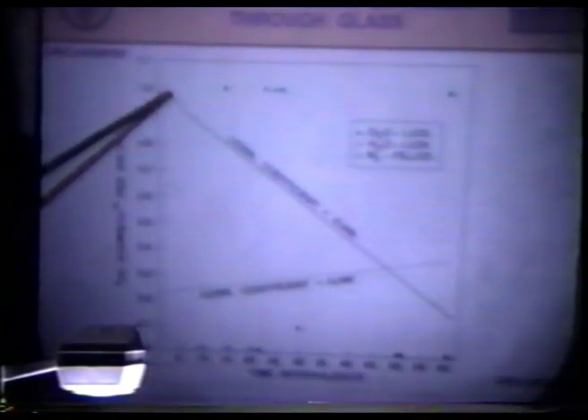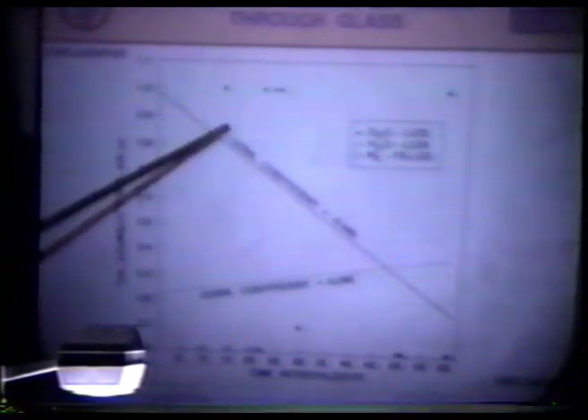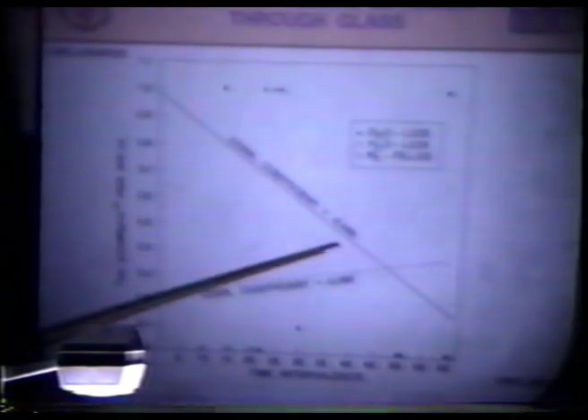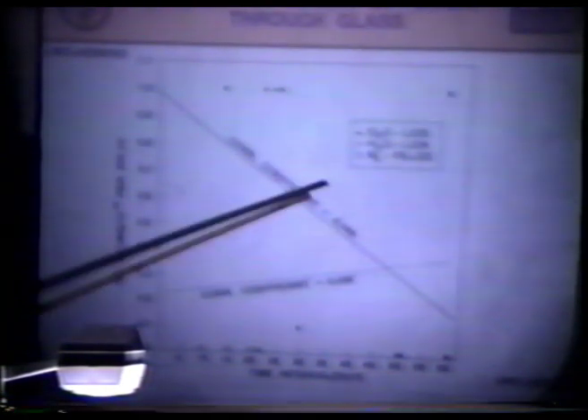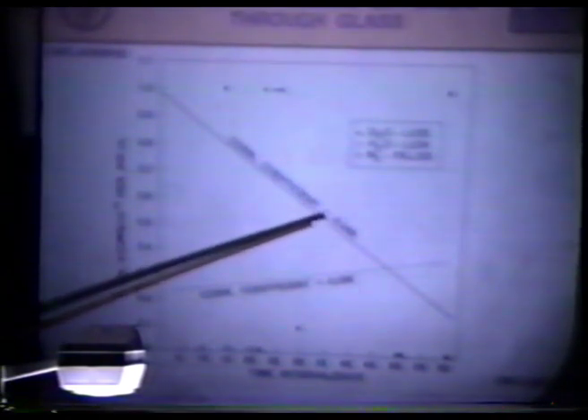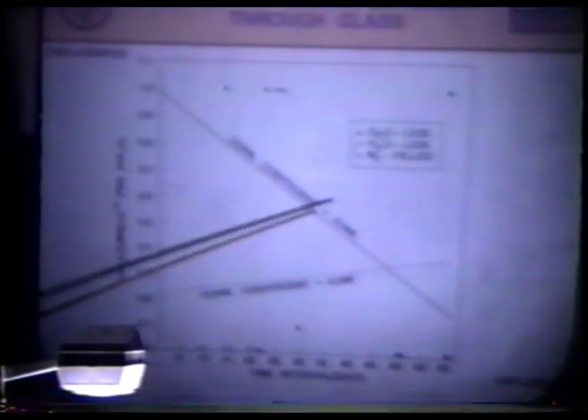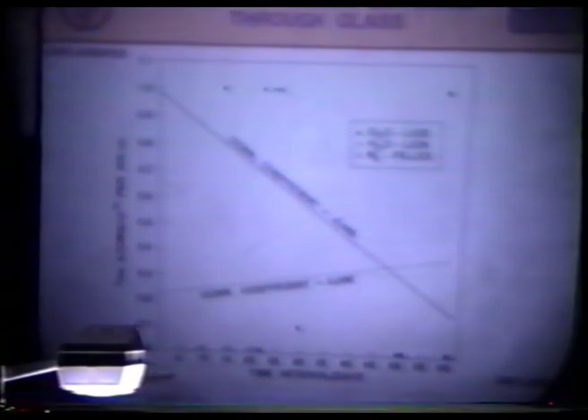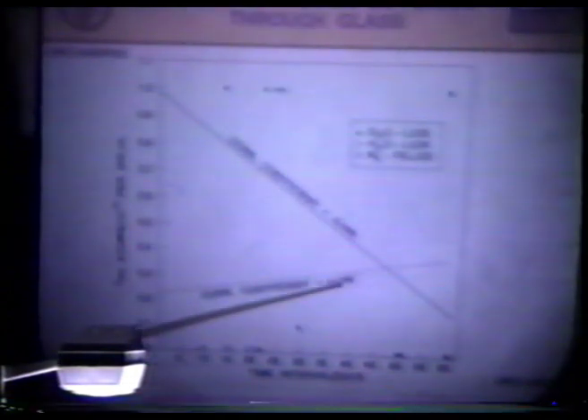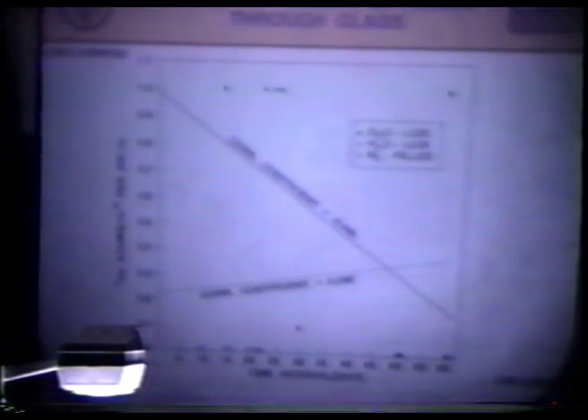If you try to draw a least squares correlation, you get a negative correlation, not a positive. There is no correlation between collection and analysis. So there is no experimental effect to support any diffusion through the glass. If you throw everything in, including the water and nitrogen, you get this straight line, which is not much better. The coefficient is very poor. But you can see that if helium diffusion through the glass were a factor, there should have been a definite correlation, and there was not.